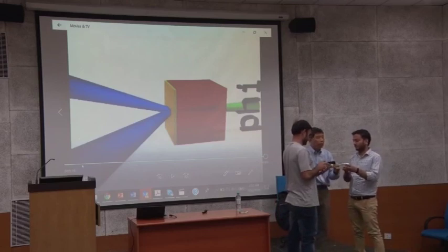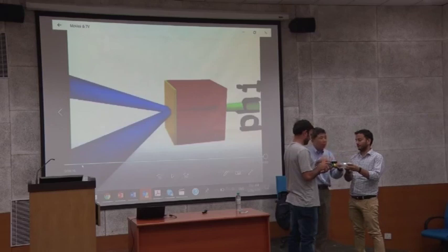I already met the diffraction condition. If I rotate this, does it change? Always this plane is perpendicular, that direction is always available, right? Okay, phi. So that means if you do this phi rotation, the intensity is always the same. No change in this case. Now you move this one from here to here, you rotate phi.